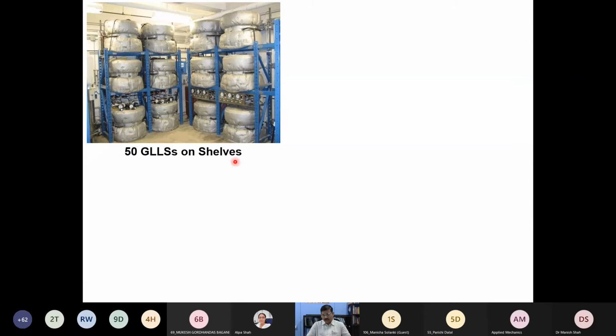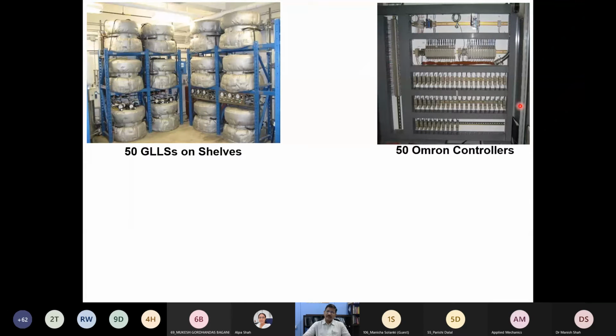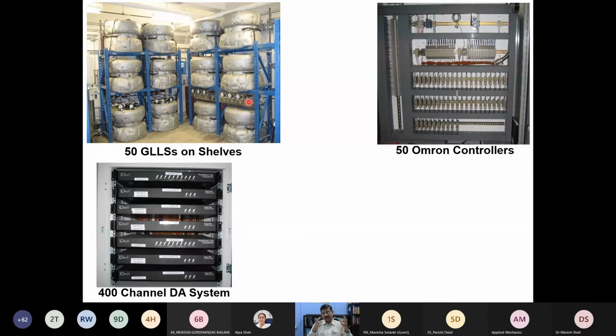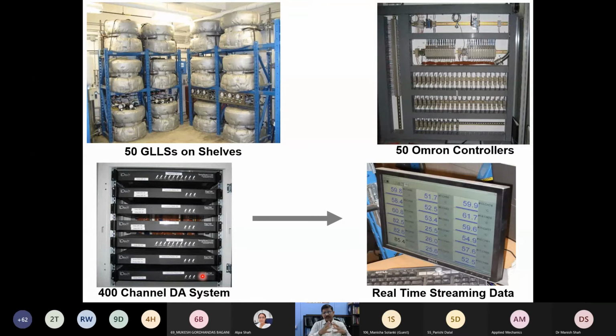Like this, we have tested around 50 of them. And then we have used around 50 Omron controllers, because we want to test a wide variety of temperatures. And then we also monitored these temperatures. For almost every cell, we erected around 8 thermocouples, and for all these 50 cells, we deployed a 400-channel data acquisition system. And fortunately, I am able to monitor this data acquisition system even by sitting at home.